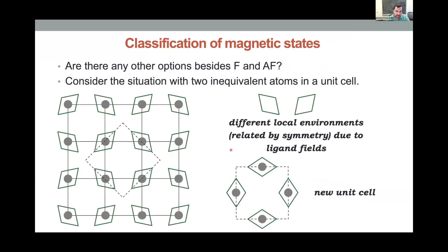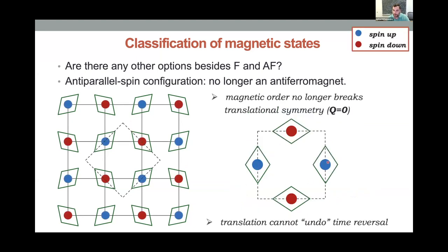Now, let's go back to this case, and let's say that now, for some reason that is not related to electronic interactions, but crystal field interactions, crystalline interactions, the local environment of these two sites are different. Right? And I'm representing these by these losangs here. So you can think of these as an octahedron, or as a cage, something that comes from the lattice. And as you can see, they are related by a 90-degree rotation. So now you see that the unit cell has twice as many atoms as the one that I started. And if I now have anti-parallel order of the spins, I no longer can apply translation to undo time reversal, if you wish. And that's because, as you can see, the magnetic order does not break translational symmetry anymore because of this effect of the crystal.